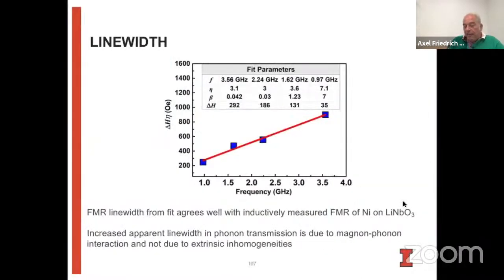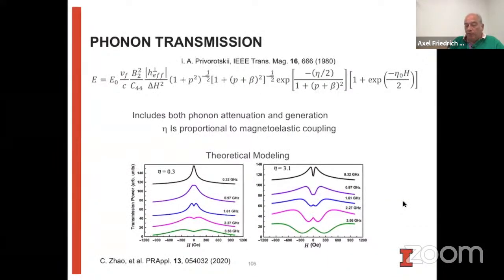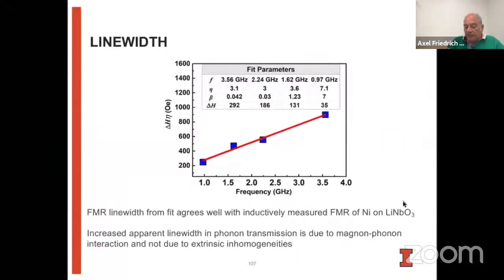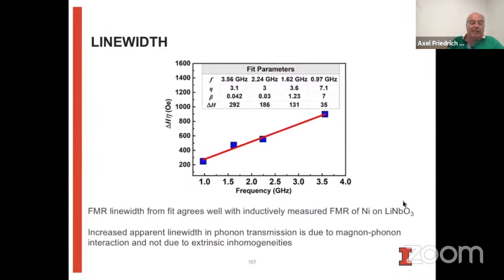But what I want to say is that when we extract the line width of the ferromagnetic resonance from this formula, it is actually consistent with what we measure of the nickel on its own in an inductive measurement. So the increased apparent line width in these phonon transmissions does not indicate that the magnetic damping of the nickel film is deteriorated, but is really indicative of the phonon-magnon coupling that we have here. Now, I should also say in these devices, sadly, we are far away from being in the strong coupling regime.